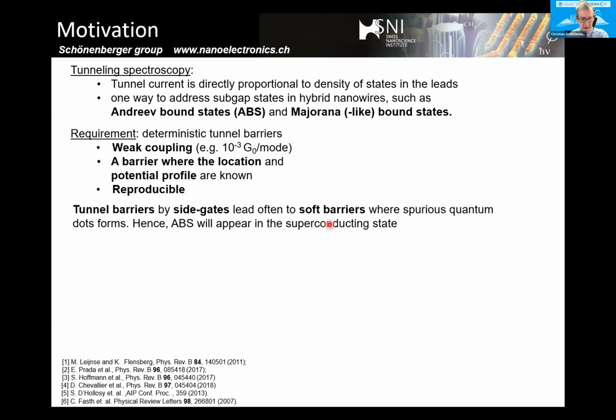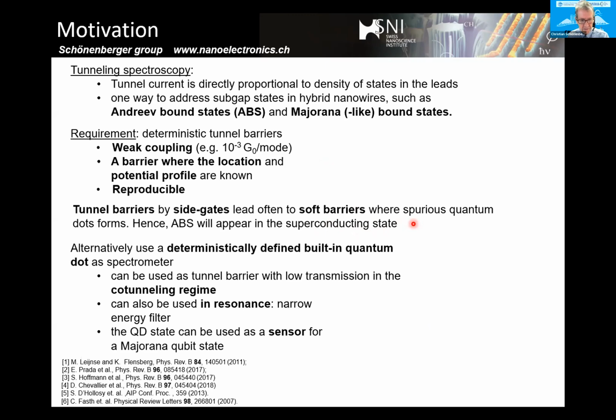And some of these tunnel barriers induced by the side gates, in particular if they're not very close to the nanowire, can induce soft barriers and then give rise to Andreev bound states. So we will be using, instead of side gates now in our experiments, built-in quantum dots. And you can use these built-in quantum dots in two ways. So the first way, you use them as tunnel barriers.